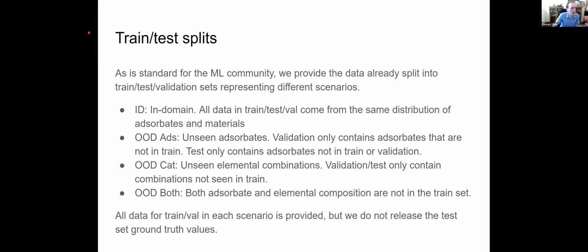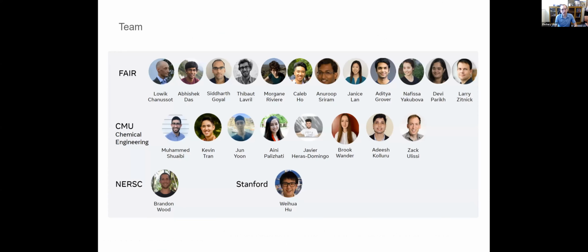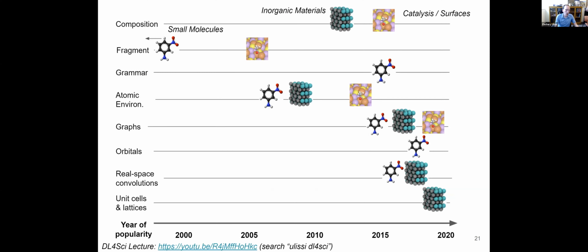Okay, another question: is there a specific advantage of using GNNs versus something else, like a force-based machine learning method or some other descriptor method or something else? Short answer is there's not a reason that graph-based methods have to be the best. The only reason I focused on them so far is that they're the only ones that, as far as I know, have worked across so many different element types. If you ask your model to predict across 45 different elements across the periodic table, it has to be able to learn why copper is different from nickel or vice versa. And the graph-based methods have been able to learn those sort of rules. Most of the descriptor methods have not done as well in extending like that.